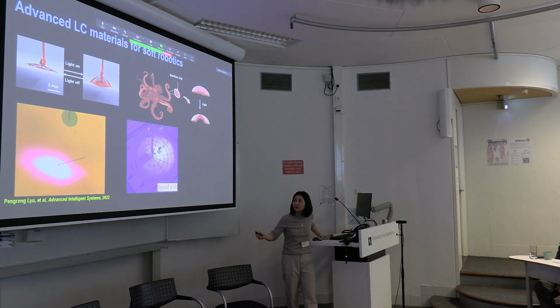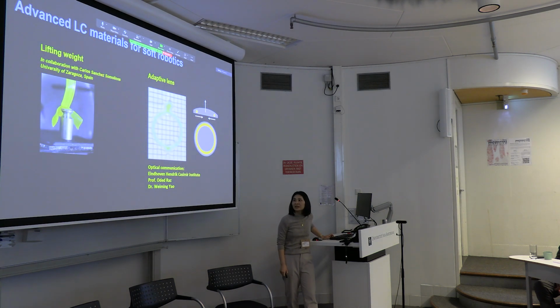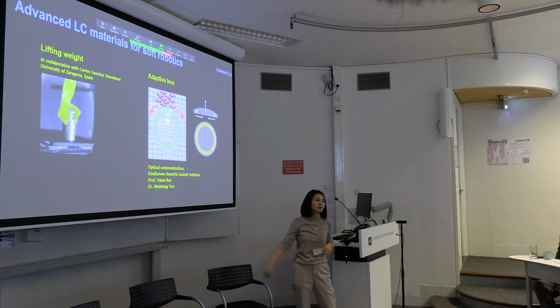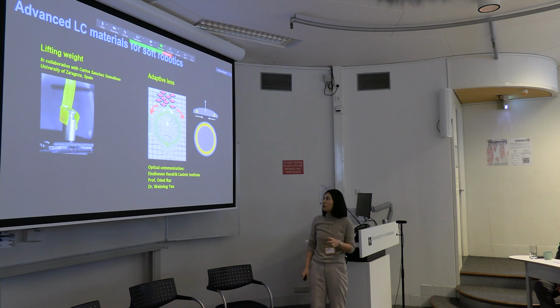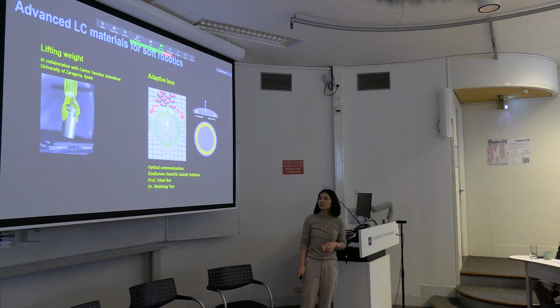Here under the UV light, what you see is the support, the parallel arm and the vertical arm made by the same material. Under the light it can pick up something, rotate, release, and go back to the initial state. Besides that, we can also make the arm grab a weight that's again much heavier than itself. And I said we can also work on optical communication. What you see here is that we're using these materials to deform a piece of rubber, and therefore we can change the depth of focus just using light or heat.